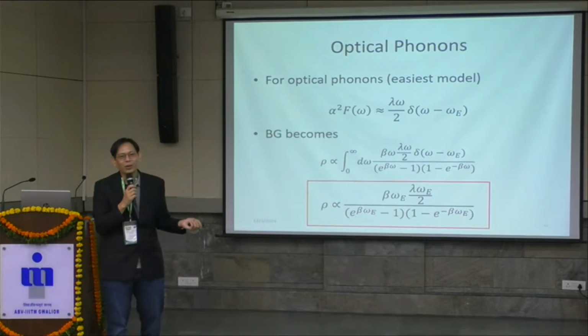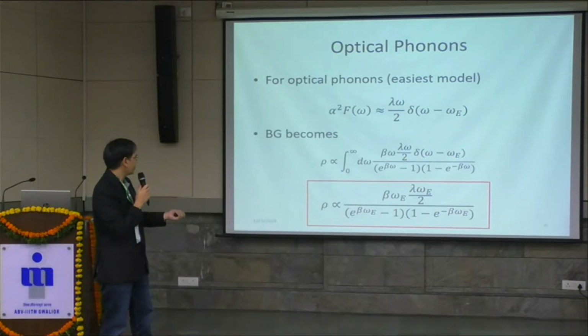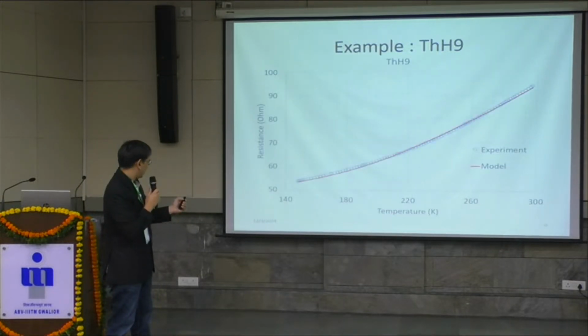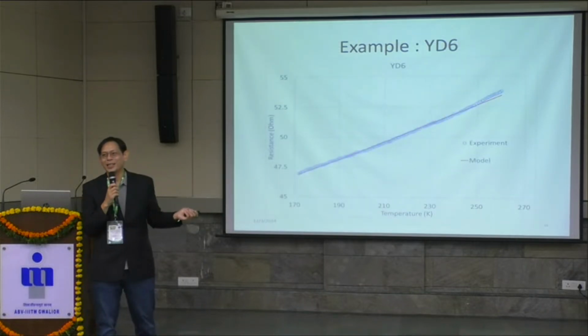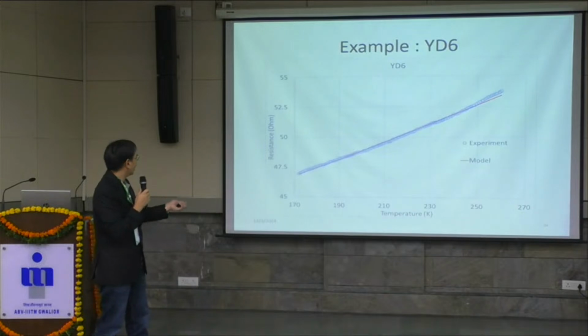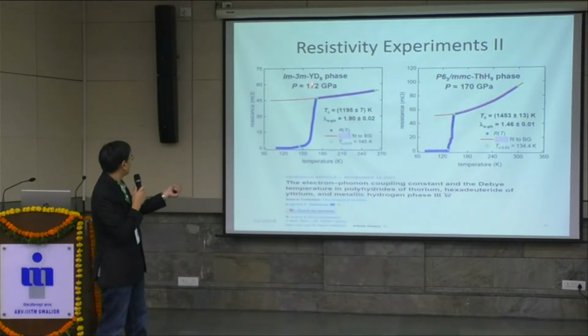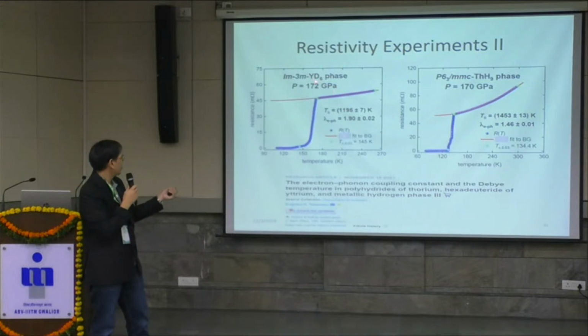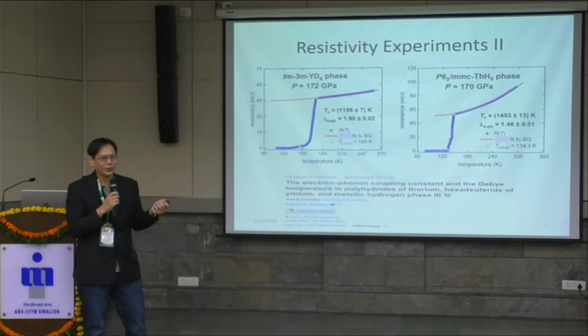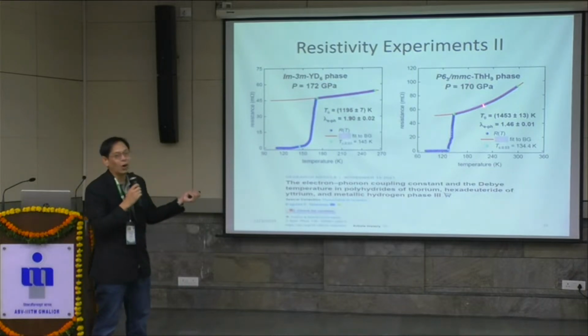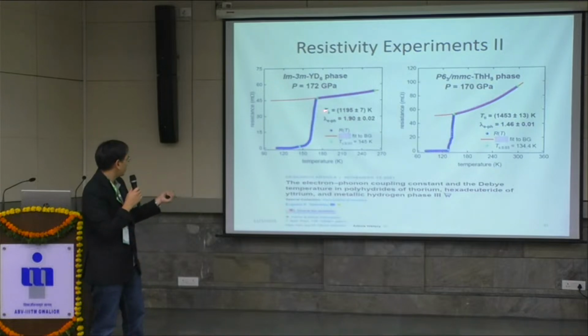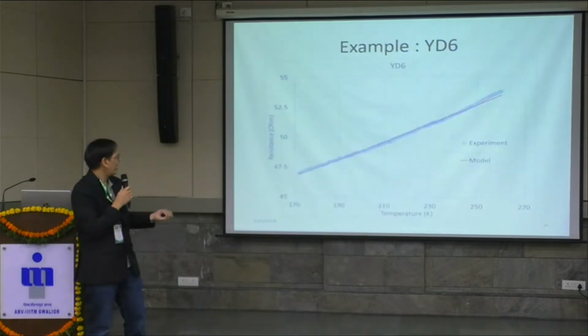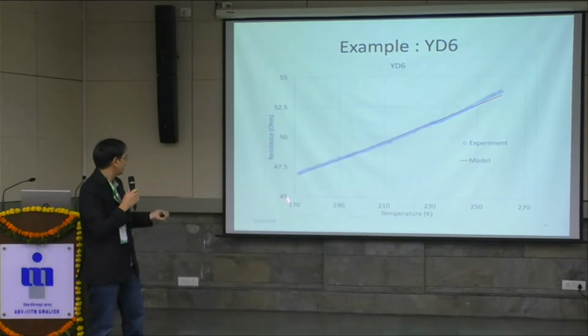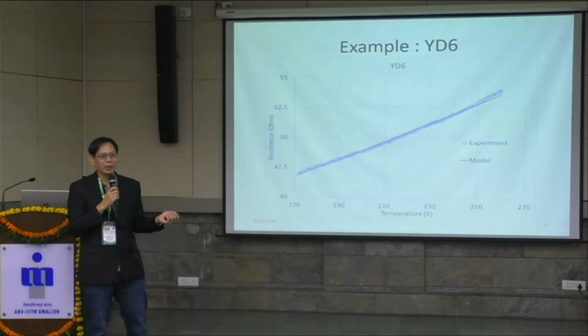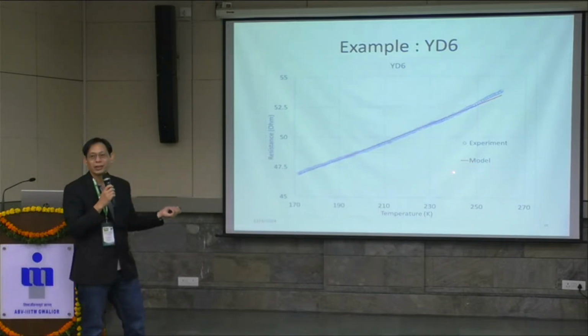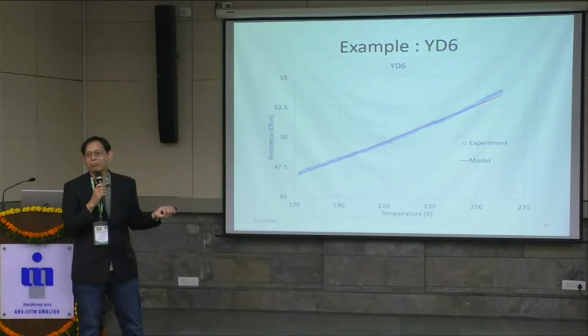It might look complicated to you, but let me show you that it can fit the experiment very well. I extracted this from the experiment. For example, this one is yttrium hexadeuteride, so it's like a yttrium hydride, but they use deuterium instead of hydrogen. And this one is a thorium hydride. They can measure the resistivity, and you can see that our model, the one that I showed you before, can fit the experimental measurement. The experimental measurement is the blue circle, and the model is the red line.